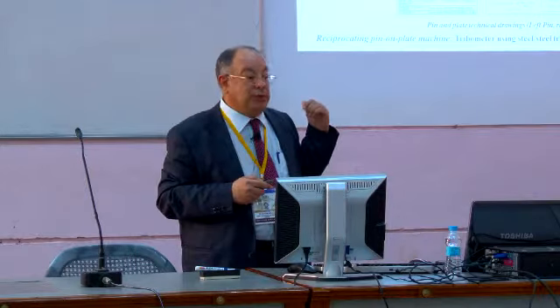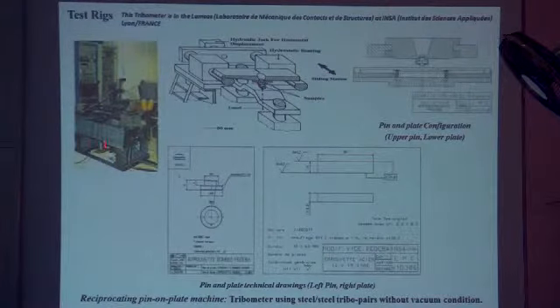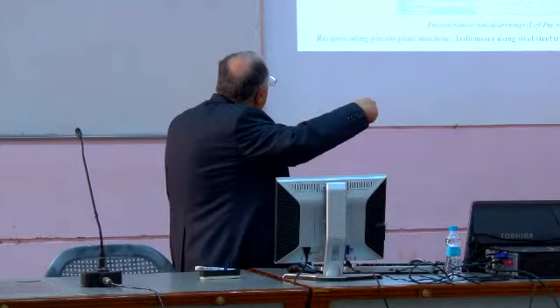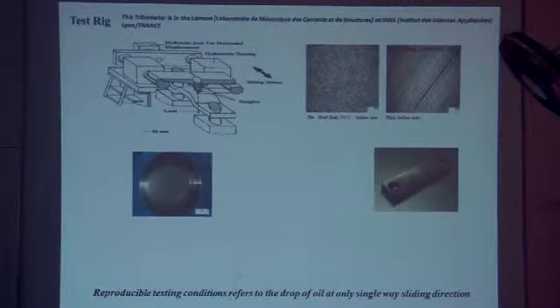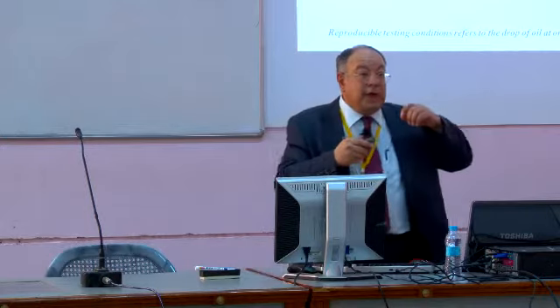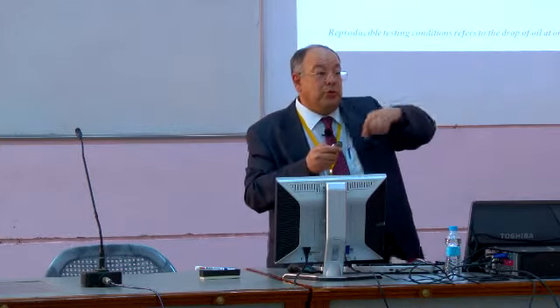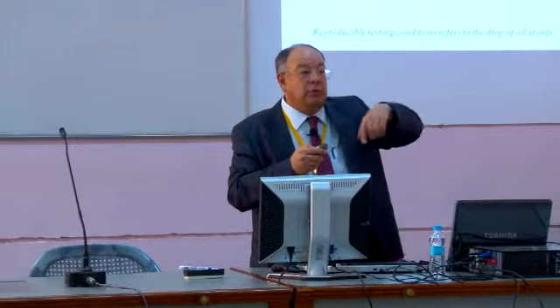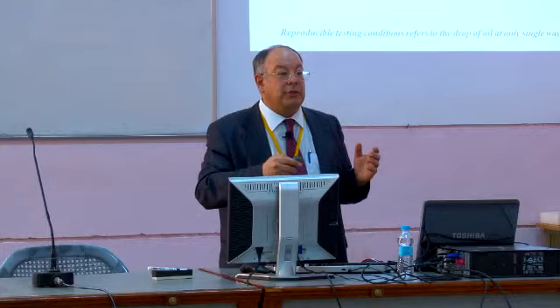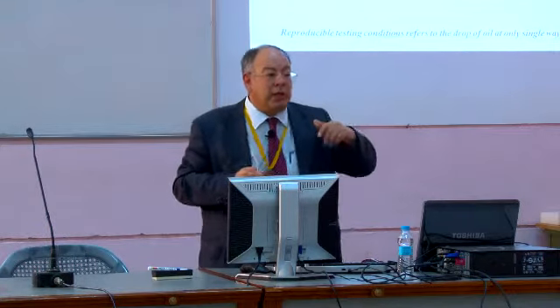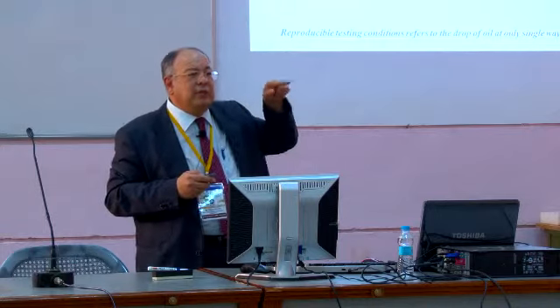In the next step, we wanted to do these tests on a pin-on-plate machine. France has a very nice pin-on-plate machine, so you can do a lot of tests. We did tests on the pin-on-plate machine with the pin and plate surface. As the movement was continuous on pin-on-disk, we couldn't be successful there. We did the same conditions on pin-on-plate, even with pin and plate, and we obtained some additive layers, but they were like islands.